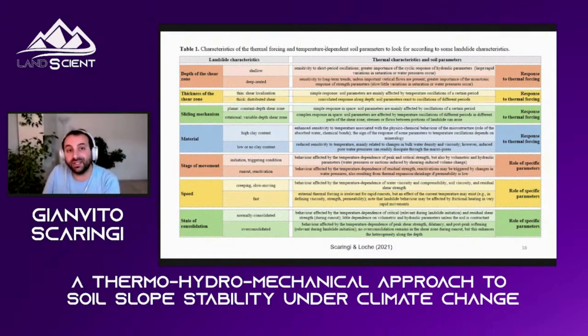Thick or thin shear zones, the effect is different. Planar or rotational landslides, clay or non-clay materials, initiation, triggering or run-out phase of landslide or remobilization, slow-moving versus fast landslide, normally consolidated versus over-consolidated landslide. We have analyzed all these aspects to try and understand the possibility of different thermal responses. So if you study an entire country and think of, okay, with climate change, the surface is going to be 10 degrees warmer. Are we going to have more or less landslides because of temperature?